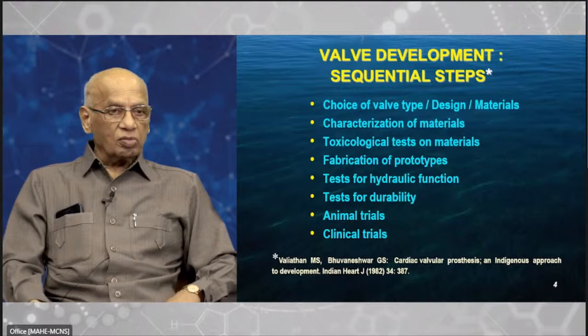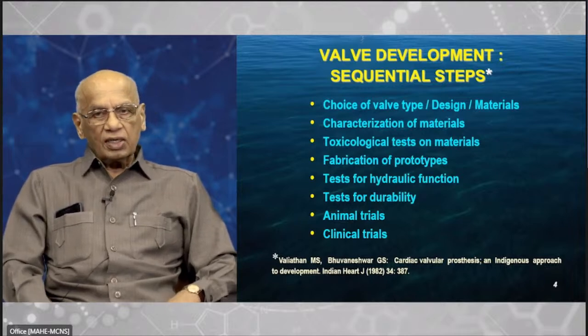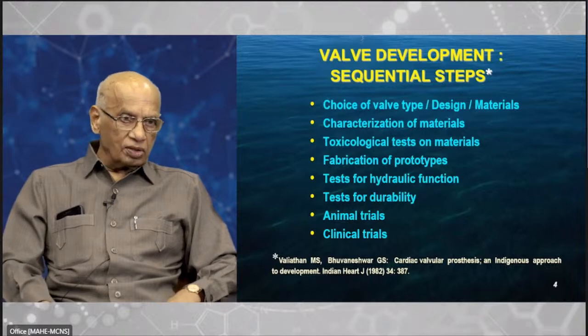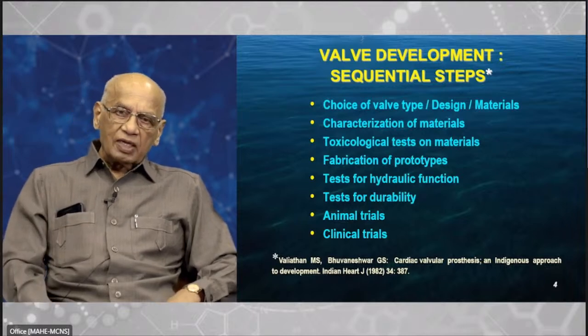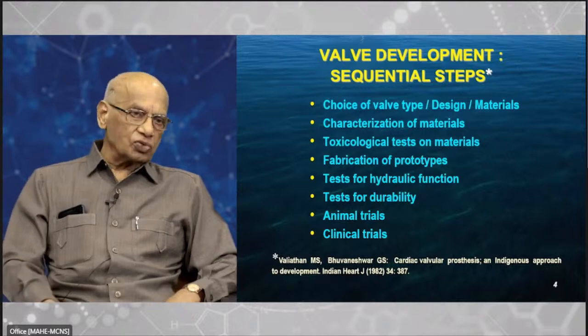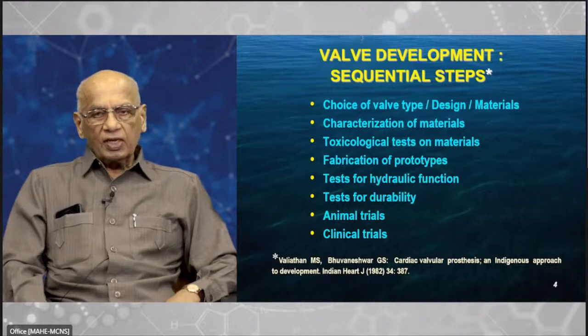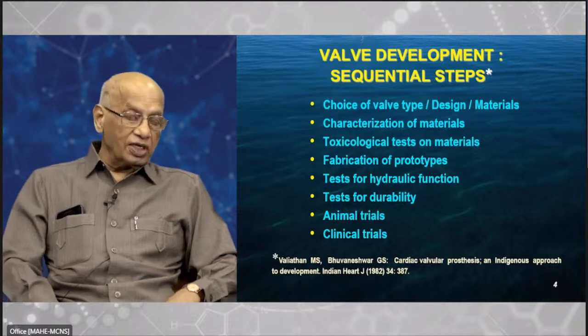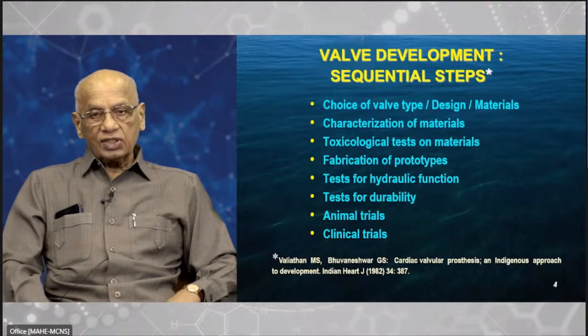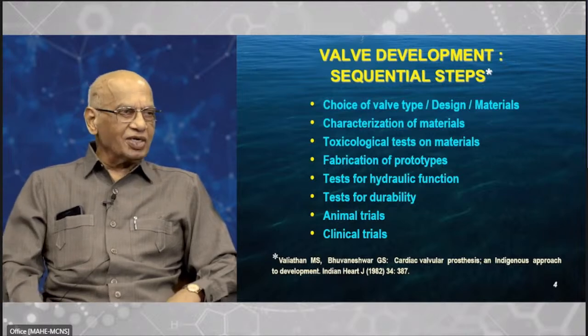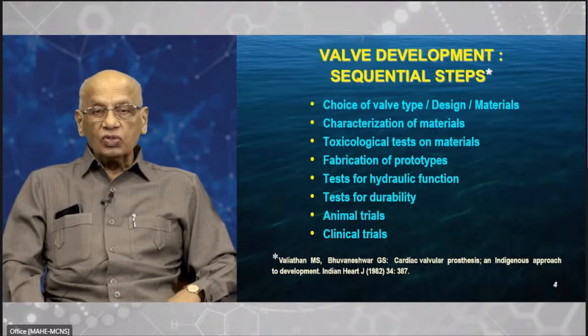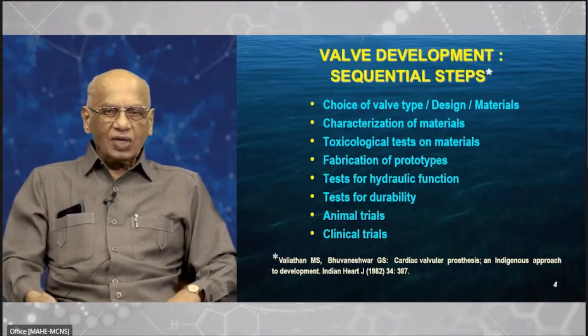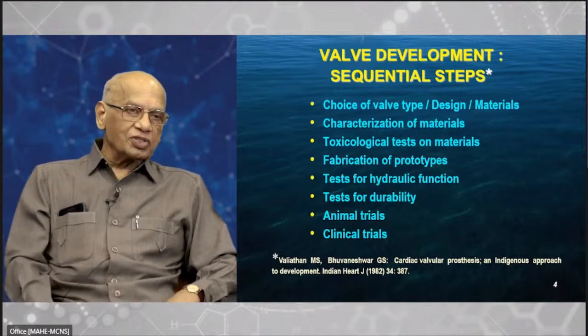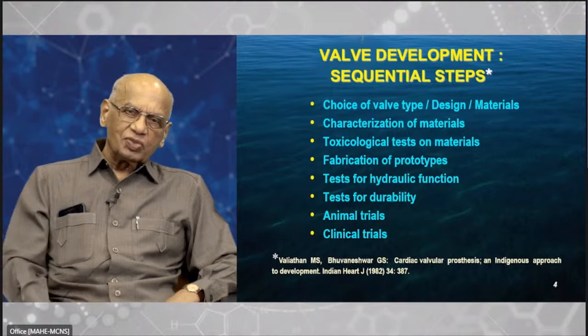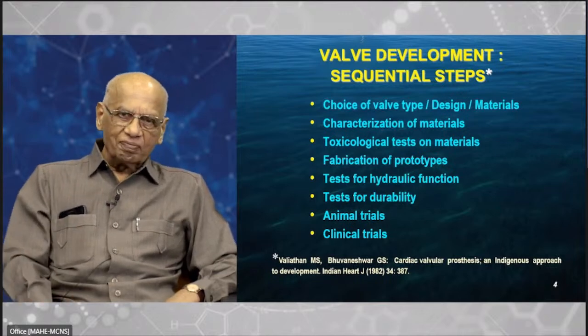And then the next test is durability. As I mentioned earlier, the international standards which we follow, ISO, there is a particular number. All valve developers have to follow this. Otherwise, it's not acceptable. Now that insists that it should have a durability of 10 years without any mechanical failure. Now that, as I said, is 367 million cycles of testing. And obviously you cannot do the test for 10 years. So we have to do acceleration. The 10 years are compressed into 1 year. So 70 per minute, we accelerate to 700 per minute. That is how it is done.